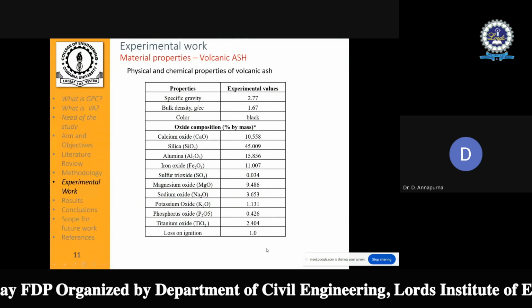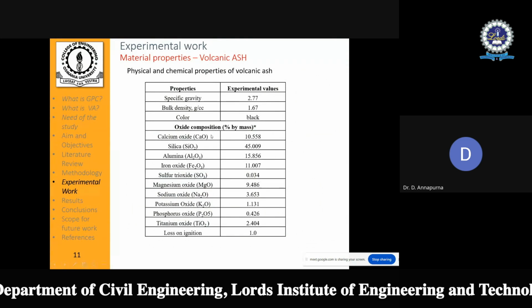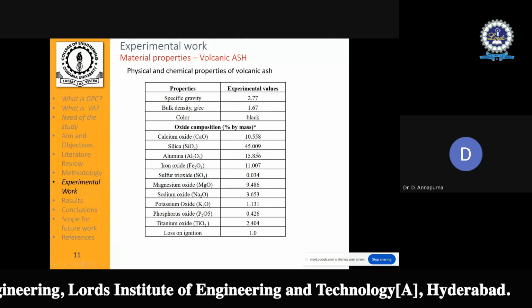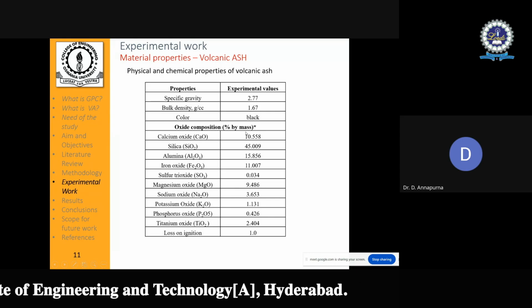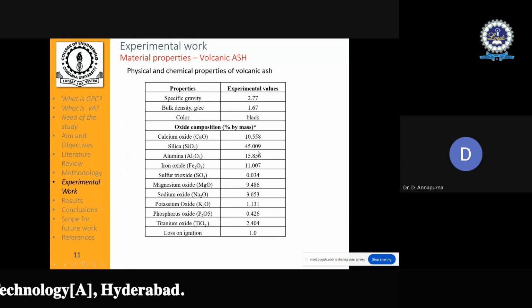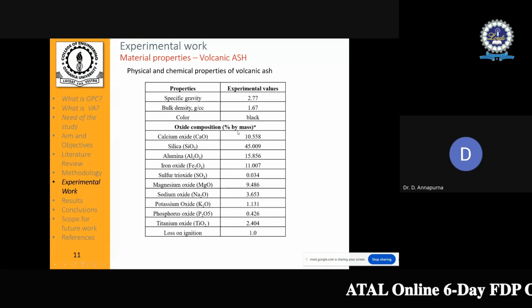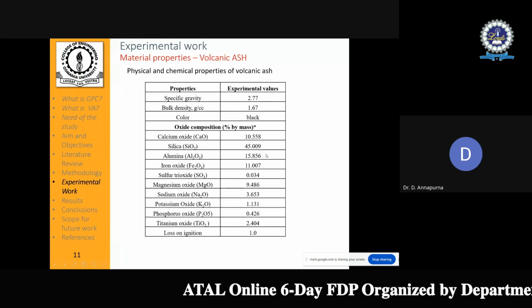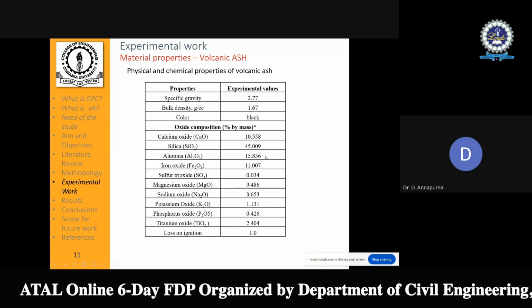And these are the properties of volcanic ash. If you look at the calcium oxide and silica, it is rich in silica. Calcium oxide is up to 10% only. It is having an alumina oxide of 15%. So like this, it is having similar properties as that of the fly ash. So this is considered as the base material.